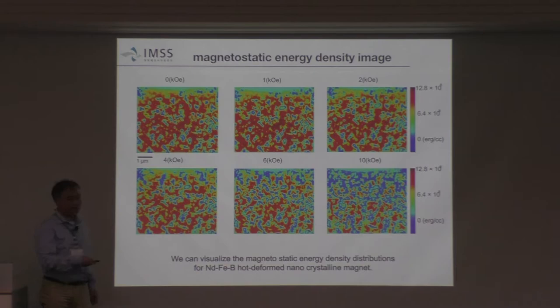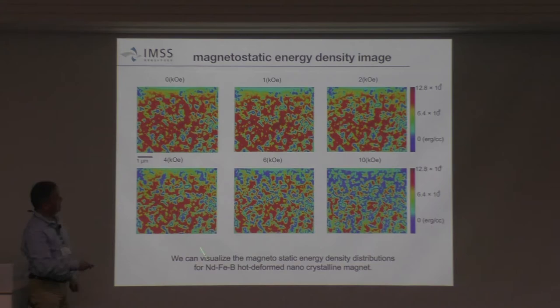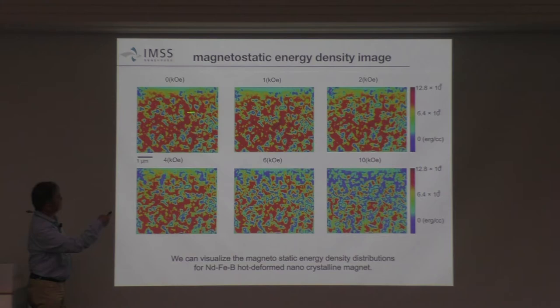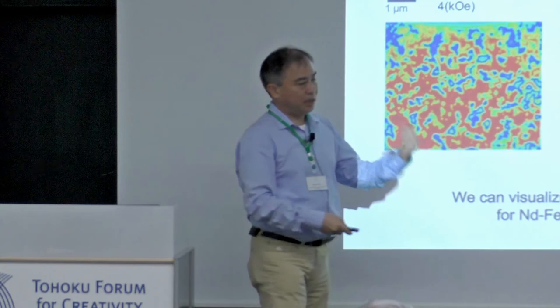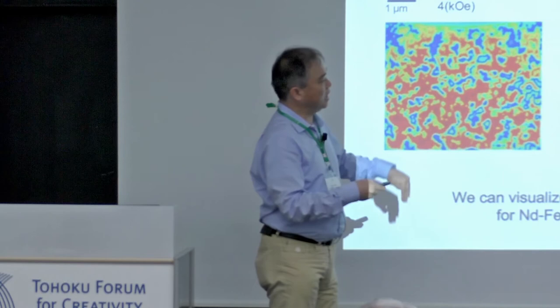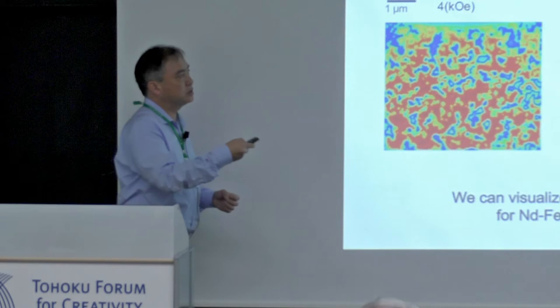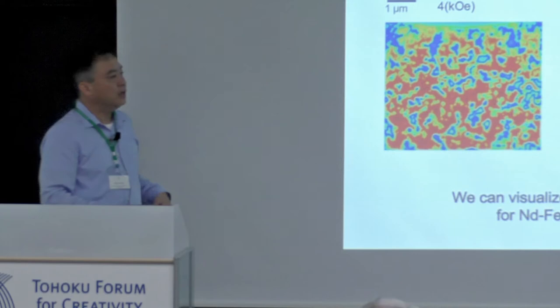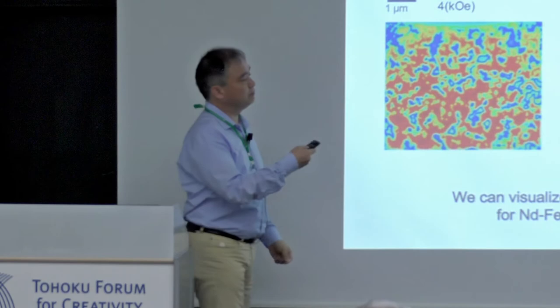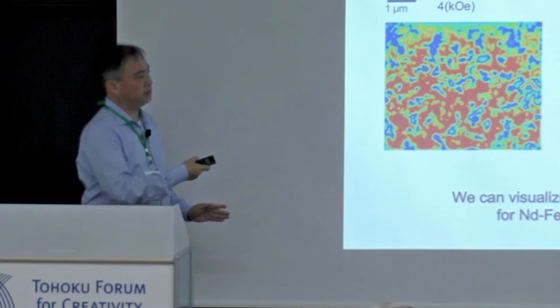Applying this modeling to the magnetization reversal image series, we can see that the magnetic stray field changes significantly during reversal. Initially the magnetostatic energy is very high; it decreases as the system rearranges to compensate and minimize magnetostatic energy. This is consistent with the well-known theory that magnetic domains form to minimize magnetostatic energy. Looking closely at the reversal process, we observe two types of processes: some individual grains reverse alone, while in other cases, neighboring grains reverse simultaneously to minimize the stray field from a magnetically hard grain that is difficult to reverse.